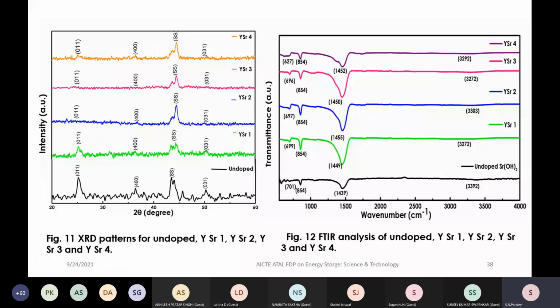After having synthesized it, we come to the XRD pattern. One can see the XRD pattern for yttrium-doped strontium hydroxide at 1 atomic percent, 2 atomic percent, 3 atomic percent, and 4 atomic percent doping. We are getting the same type of peaks. Slightly the nature is changing due to the doping, and in the FTIR analysis also one can see the same type of structure, slightly changed due to the doping.